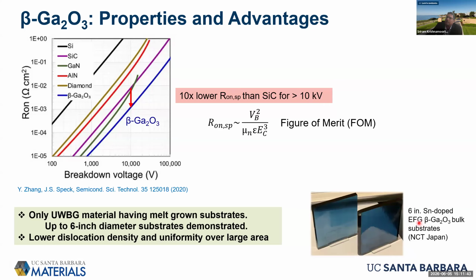Essentially, this edge-fed growth technique is the same technique that's used for pulling sapphire from a melt. And we all know how sapphire scales well to larger areas, and it's low cost. So eventually, with enough volume, this could be a great thing to have, a bulk substrate technology that can be scaled to larger areas, because power devices, especially those required for high voltage applications, generally also need high currents. So the devices themselves are going to be huge, and having a bulk substrate platform is going to be very important. It's the only ultra-wide bandgap semiconductor that can be pulled out of a melt and still doped N-type. So you can get N-type doping control over a large range, and large area substrates are available.